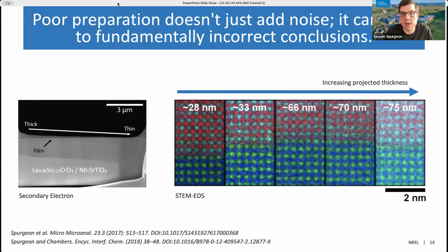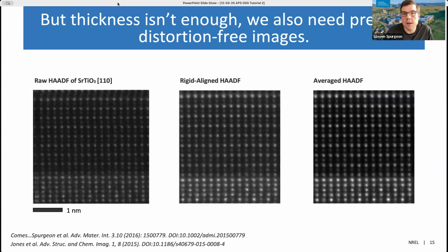And so on the right here, what I'm showing is a sequence of different processing conditions on atomic resolution spectroscopy of an oxide heterostructure. So one of these integrated heterostructures that I showed. The idea here is that depending on the thickness of the sample and resultant beam interactions with the sample volume, you can get delocalization of signals, essentially artificial broadening of interfaces, reduction in signal to noise in your maps that are all just purely artifacts from sample preparation. And so if your goal is to train a machine learning model or any type of statistical model to analyze these interfaces, you need to be able to mitigate and to control for this so that you can ensure reproducibility from experiment to experiment.